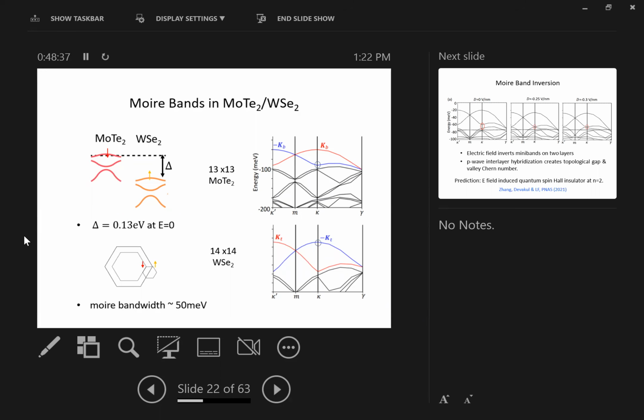What we do is we can first put the two layers together and optimize their structure. Then each layer is corrugated, and we can take the corrugated lattice of one layer and remove the other layer. So we can look just at the Moiré bands formed in one layer in the absence of interlayer tunneling. Why we want to do that is because the interlayer tunneling is a small perturbation in this system, for reasons I'm not going into in detail. But this will help us analyze how the bands evolve.